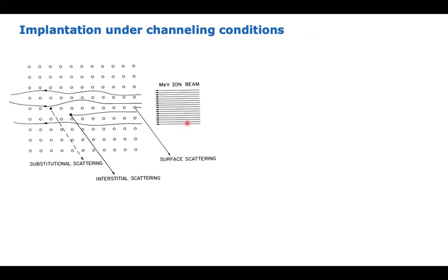What is important in this case is that you can exploit this channeling to understand the material. Let's say I have already doped, implanted some of the ions. If you do the channeling measurement, you will be able to understand where these implanted atoms are sitting: is the implanted atom sitting in an interstitial position or in the lattice positions, just by looking at the backscattered ions. In that case, you use very low Z ions, for example helium ions, which have lower mass and can really penetrate, and the interaction is relatively lower. So you get the backscatter signal. You keep your detector, which can count the backscattered ions, and then you see how the number of ions that you collect changes with energy.